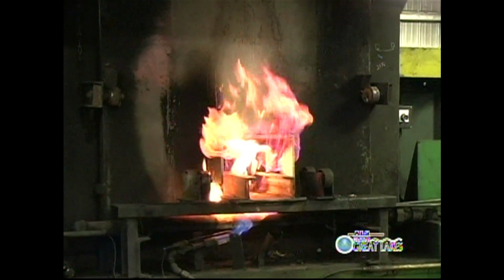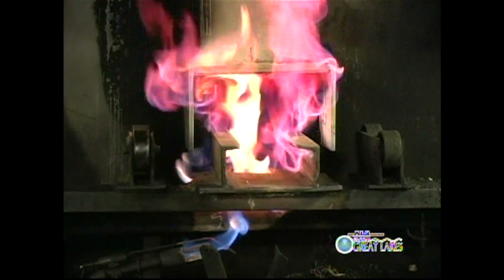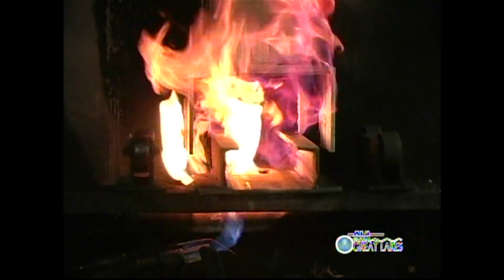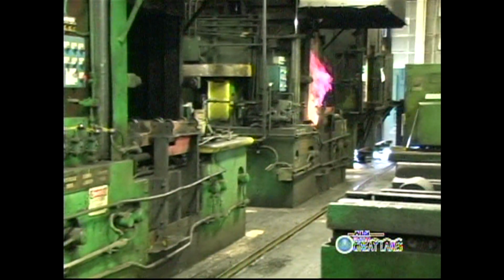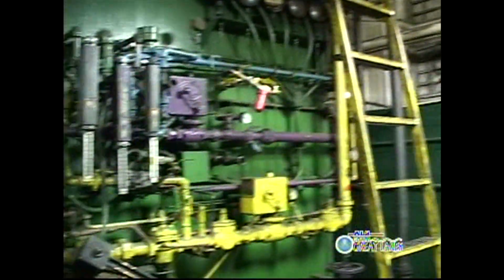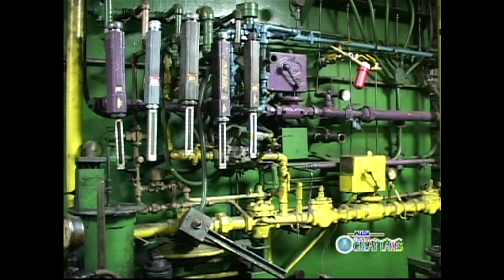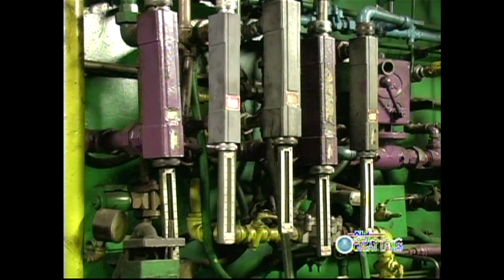These furnaces have a special gas that we make here in Industrial Steel. It's endothermic gas that we make in our generators, where we take air and natural gas and superheat it to 1800 degrees, and it cracks, and then we critically cool the gas to form endothermic gas, which consists of hydrogen, nitrogen, and carbon monoxide. As you can see, these flow scopes control the amount of gas that we have in the furnace: endothermic gas, natural gas, air, ammonia, depending on what the process that you want to put these parts through.